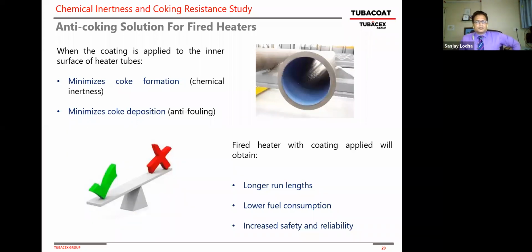So the coated tubes have two things that work very well for the heater tubes. One is these coatings are chemically inert, so they minimize the coke forming reaction. Second part is, once you form the coke, does it stay in the coker furnace tubes or does it move further to the coker drums? It has this anti-fouling, very smooth surface that allows minimum coke deposition. Because of these two properties, you get significantly longer run length between the spallings or decokings. Since the surface is much cleaner, your fuel consumption is lower. And since you don't have that many spallings and piggings, there is improved safety and reliability. So the advantages are very well explained.